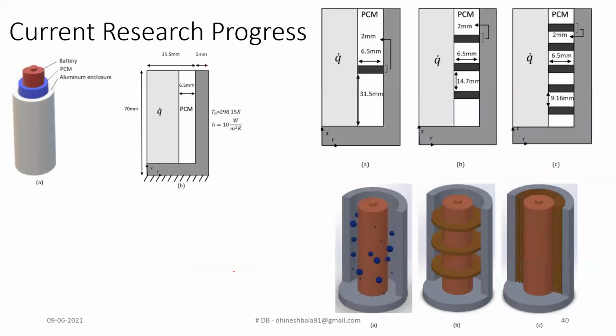temperature limit. But we have not yet achieved the optimal temperature range of 15 to 35. But just by introducing PCM along with metal foam, we are able to achieve this particular point. Whatever cell I have presented here is a rectangular type of block. And the current research progress is that they are trying to incorporate a phase change material and an aluminum enclosure. So you'll have an aluminum enclosure, close to it a PCM module, and inside it you will have a battery cell.